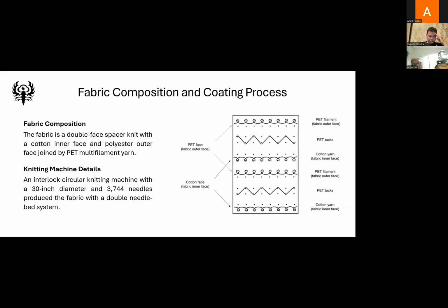This is the fabric they use, the double face spacer knit, with the inner face using cotton fibers for comfort, and the outer face using polyester, and the spacer using polyester multifilament yarn. They make this knit fabric on an interlock circular knitting machine with a 30-inch diameter and 3,744 needles. We can see the construction of the fabric in the figure.